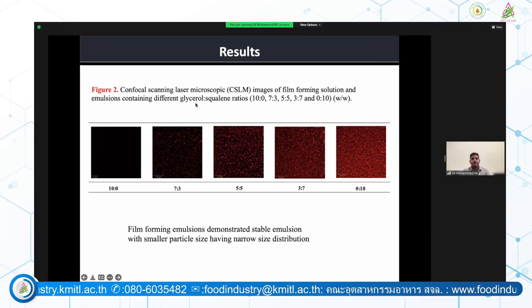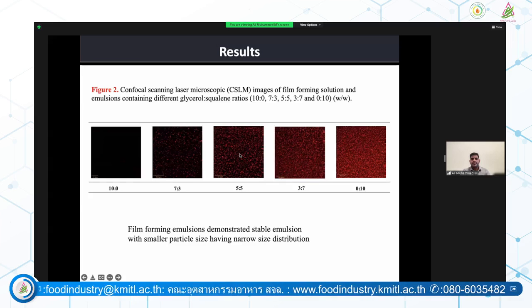So these are the confocal images of film emulsions prepared by replacing the glycerol with squalene at various ratios, where you can see the highest ratio of glycerol and the highest ratio of squalene. We could see there is no droplet distribution of squalene in glycerol, and as the concentration increases, we could see higher droplets at nanoscale evenly distributed in the solution. So this indicated that ultrasound had good emulsifying property with squalene.